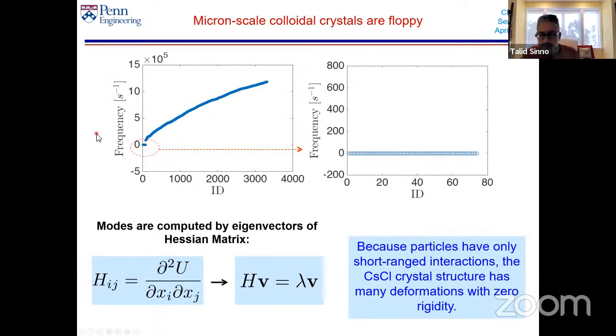So let me just briefly walk you through what we tried to do here. We wanted to study this transformation pathway. And if you do a mode analysis on these crystals, you find that there's a whole bunch of zero modes. Zero modes means I can twist or deform my crystal along certain eigenvectors at zero energy penalty. So in other words, these crystals are floppy. And this is what allows them to transform from cesium chloride to close packed. So in this crystallite, which was, let's say, about 1,000 particles, I have 3,000 different eigenvectors, of which about 75 are zero modes.